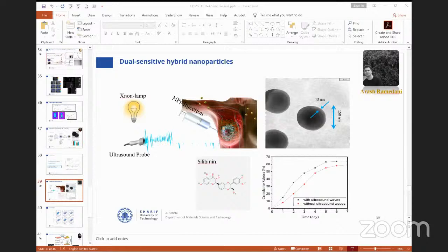We used silibinin as a model drug and prepared the nanoparticles. The nanoparticles were based on liposomes, so we use a special liposome system. Inside the liposome, we put the drug, and the outside layer is a thin layer of graphene quantum dots, so it can be imaged. The polymer which we used was a piezoelectric polymer based on PVDF. So it's a very complex system, liposome, PVDF, and quantum dots of graphene, in order to create multifunctionality.